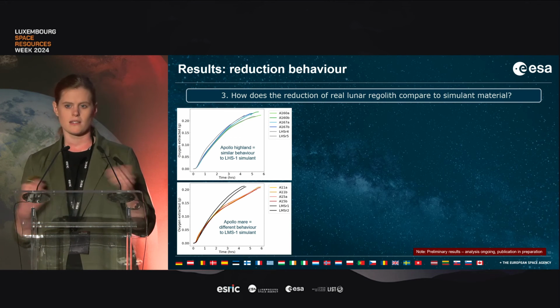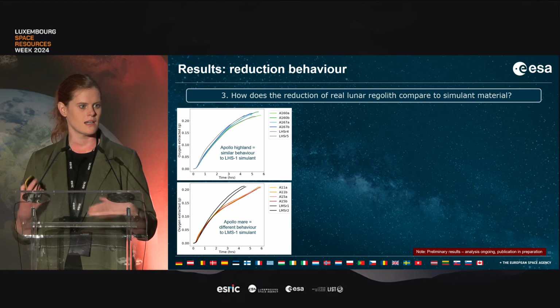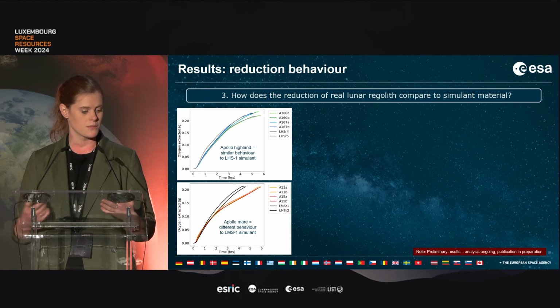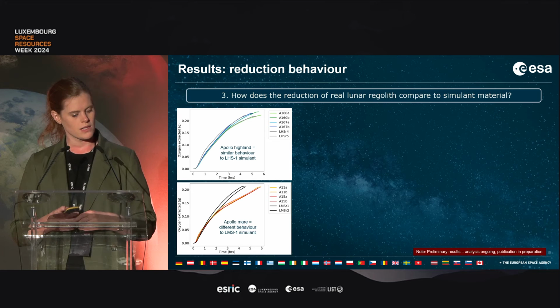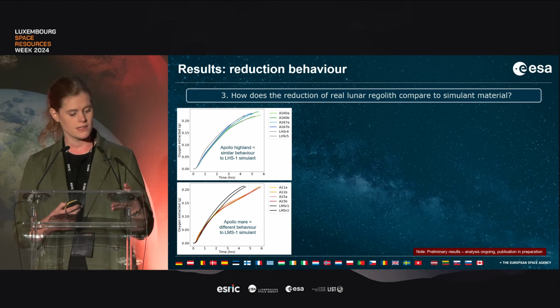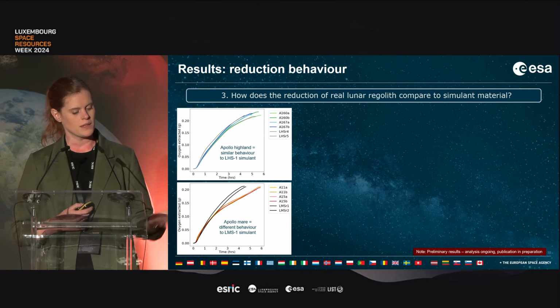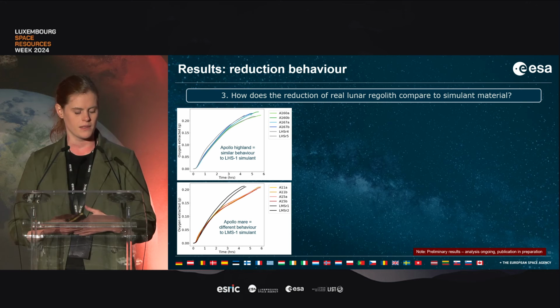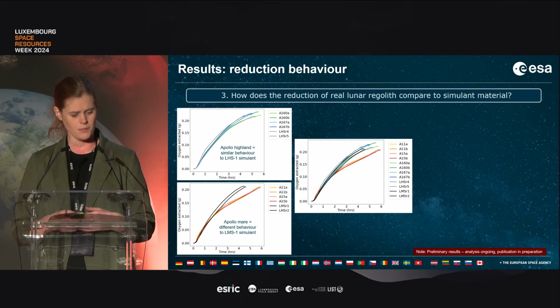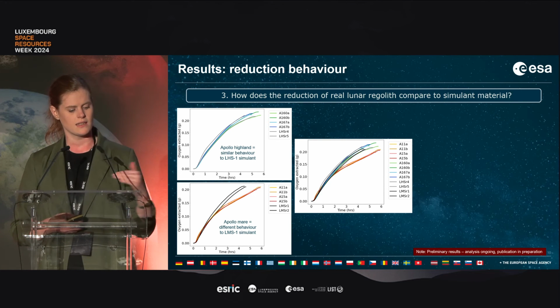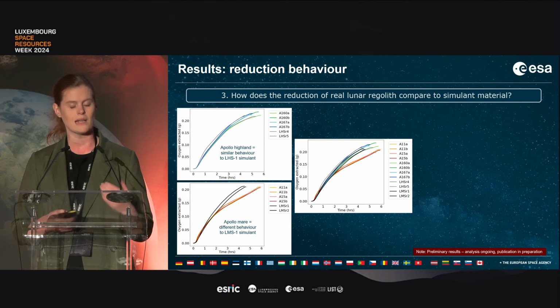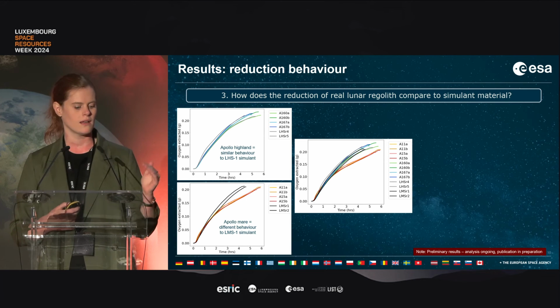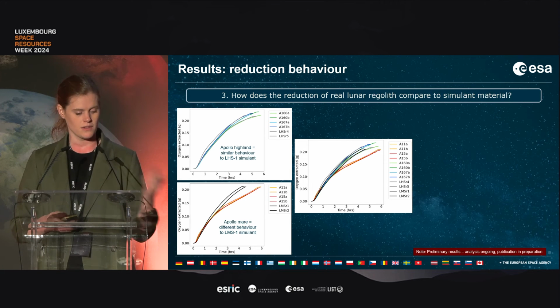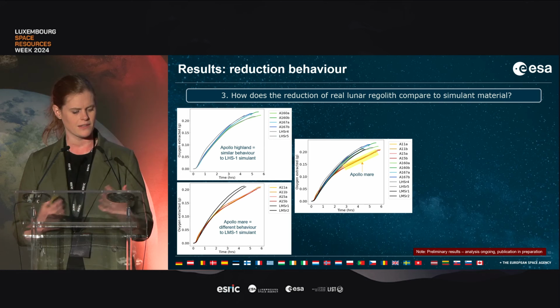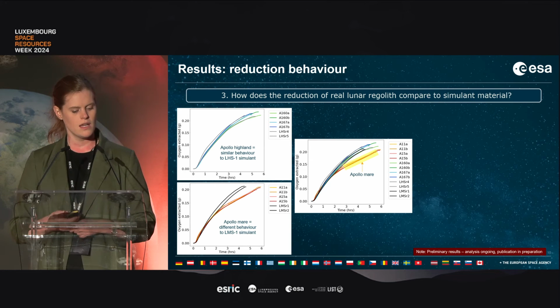Then looking at how the reduction compares to the simulant material, which is important to understand how we can use those simulants in the lab to optimize the process. The Apollo Highland material was very similar to the LHS1 simulant, but the Mare material was quite different to LMS1 simulant. Putting those onto one chart, you can see that the LMS simulant behaves more like the Highland material, for the simulant and the Apollo samples. So the outlier is really the Apollo Mare material here.